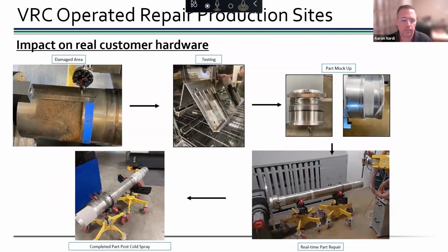And what we can do there, here's an example. This is a shaft. Steel shaft needs to be repaired. You can see bad corrosion damage on it. So you do all the testing up front to qualify your process. Then we typically make a mock part or something that looks close to that part, especially if it's a unique geometry. This is a pretty simple geometry, but we still did a mock part because you can see there's some fairly deep areas, deep severe damage. So we wanted to make sure we could fill and then do a more uniform coating across the entire thing.